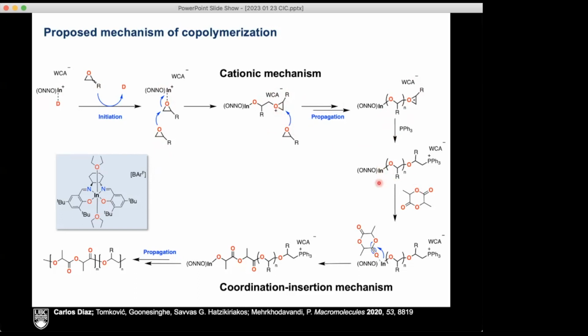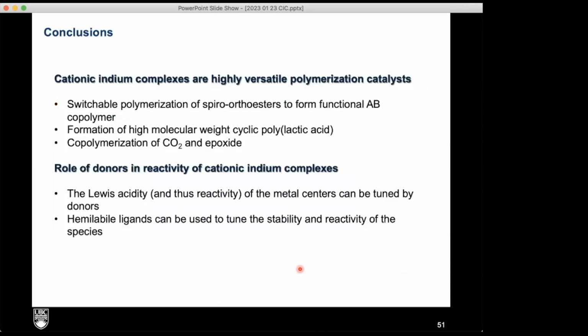So now all we end up with is a neutral indium complex alkoxide, which we know is a really good catalyst for lactide polymerization, which then goes ahead and polymerizes the lactide, and it allows us to get these beautiful controlled block copolymers, which also Carlos was able to show that he can actually tune the physical properties of these polymers, like their Young's modulus and the rheology, depending on what the different components are. So with that, and since my voice is about to die, I'm gonna conclude,